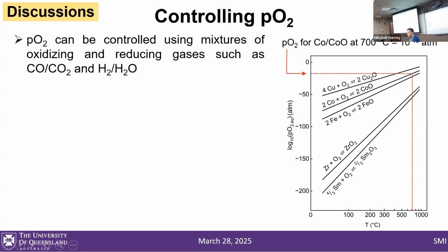For example, the cobalt oxide line at 700°C has an equilibrium oxygen partial pressure of 10 to the negative 18 atmospheres. That's incredibly low—you're never going to get this oxygen concentration just by diluting oxygen with argon or some other inert carrier gas. So how do we get there?